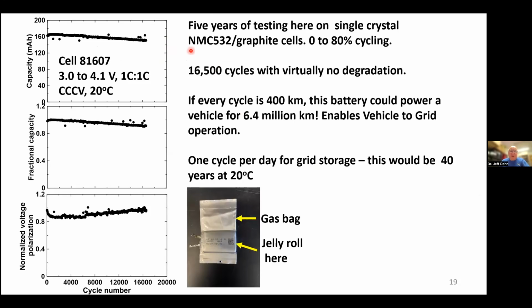So here I'm showing you 5 years of testing on single crystal NMC 532 graphite cells. These cells are charging in 1 hour and discharging in 1 hour. They've been going for 5 years. They're going from 0% fully discharged to 80% charge, 16,500 cycles with virtually no degradation. If every cycle represented 400 kilometers of driving, this could power a vehicle for 6.4 million kilometers. And nobody's going to drive a vehicle that long.